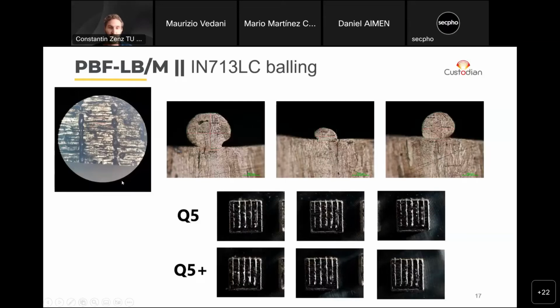single track experiments, and you can see that we have an unconnected weld bead of sphere-like structures. And so the substrate wasn't really penetrated well, and the liquid couldn't wet the substrate, and therefore we see these high contact angles in the liquid, and then it solidified and formed these unfavorable cross sections.